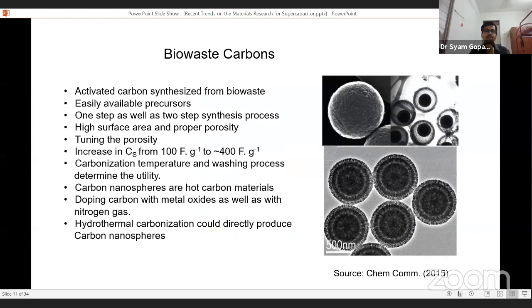So with that bio-waste, usually the capacitance range for this activated carbon will be from 100 to 150 farad per gram. But by tuning the porosity of this bio-waste carbon, the maximum capacitance achieved is around 400 farad per gram. That means the carbonization temperature as well as the washing process determine the utility of this bio-waste carbon for this supercapacitor application.